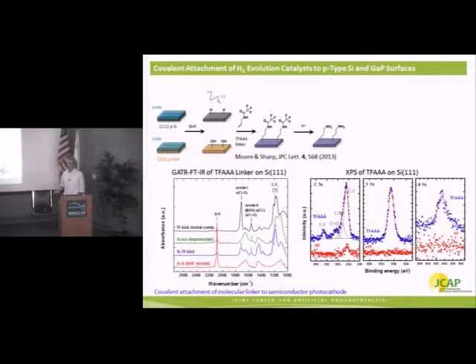So now we're investigating the same chemistry, namely a reaction of this terminal alkene molecule with two different types of surfaces. One is hydrogen terminated, one is hydroxyl terminated. And what we find through both FTIR and XPS measurements is that the chemistries work similarly on the two surfaces, except we have a carbon-silicon bond to the substrate in the case of silicon, and an oxygen bridge bond to the gallium phosphide substrate in the case of gallium phosphide.